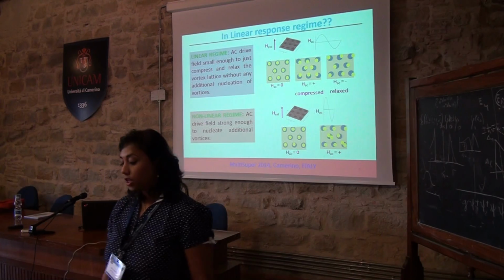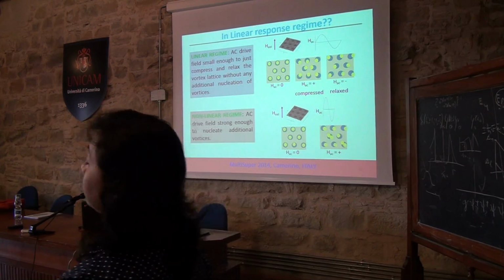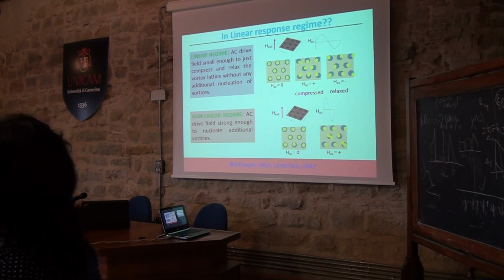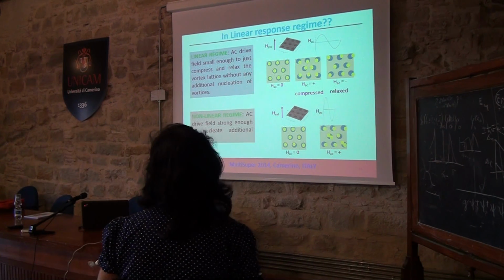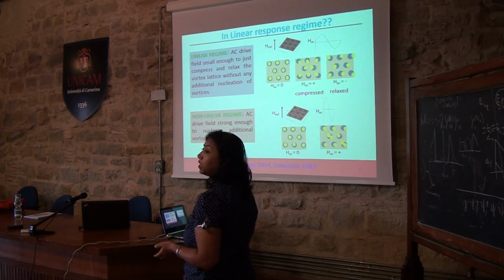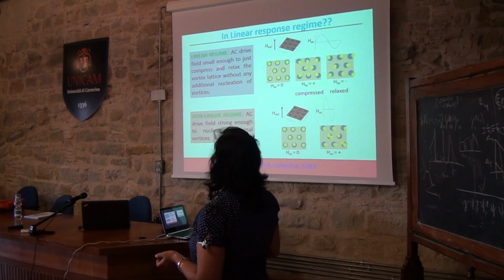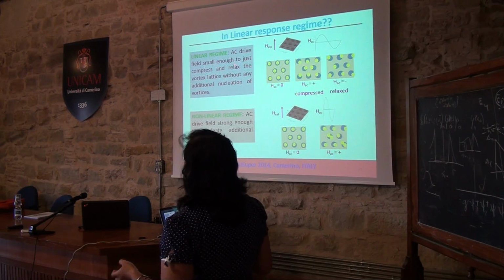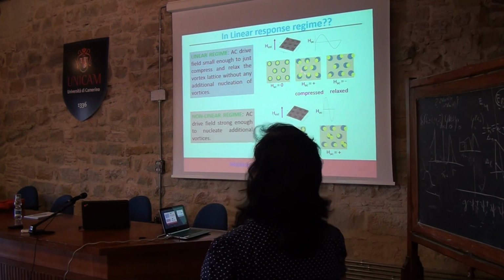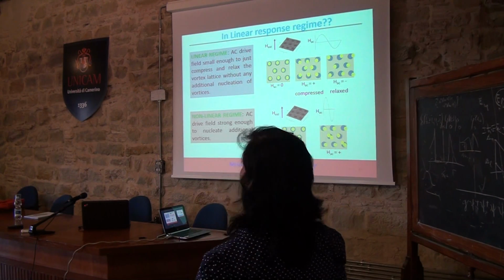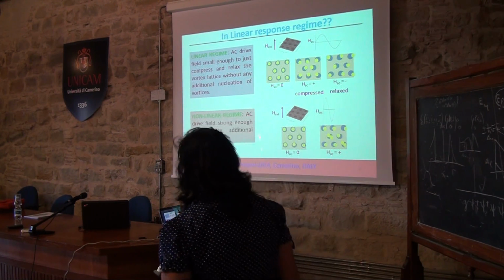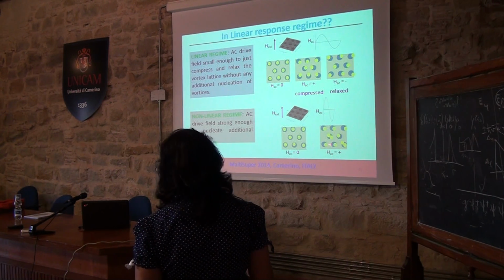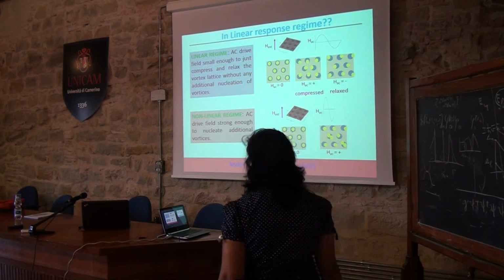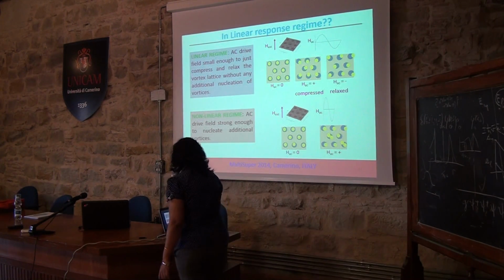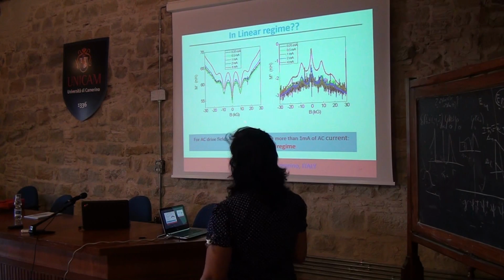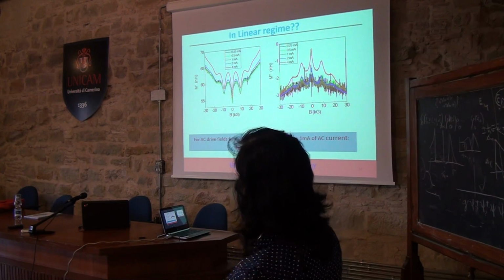Before I show the results for all my samples, we wanted to convince ourselves that we are working in the linear response regime. That is, your AC drive field is small enough so that we are not nucleating any additional vortices. If the AC drive field is quite small, then what it will do is just compress or relax the vortex lattice without any additional nucleation of vortices. But in the nonlinear regime, you will start nucleating additional vortices in the antidots, and then the entire premise of commensurate healing will fail.